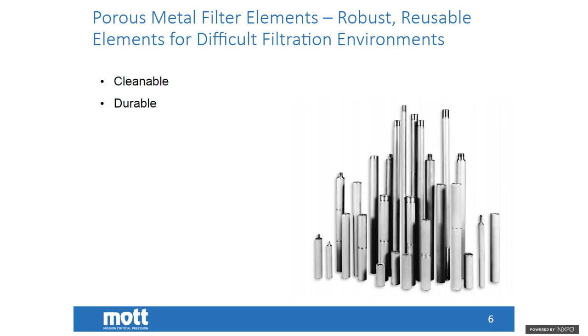They're durable — these are stainless steel, approximately 30% porous, so they may not have the yield strength of solid stainless steel, but they can be welded and can withstand significant bending forces, collapse pressures, and burst pressures. They're corrosion resistant; stainless steel elements offer corrosion resistance, but we also have other alloys available such as Hastelloy C22 or C276 for specific corrosion concerns. These elements are also self-supporting, which allows us to use the inside of the element as valuable space to the filtration process.